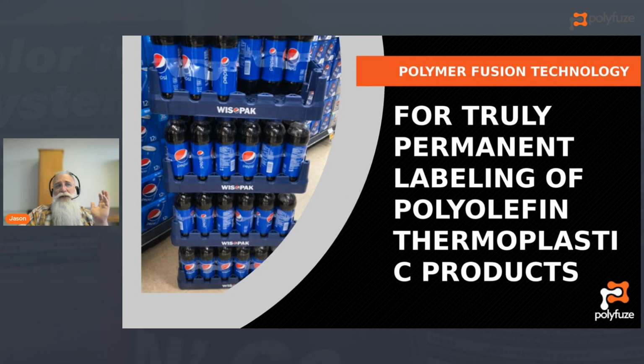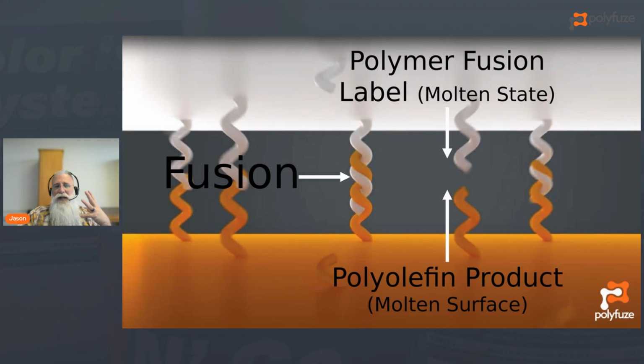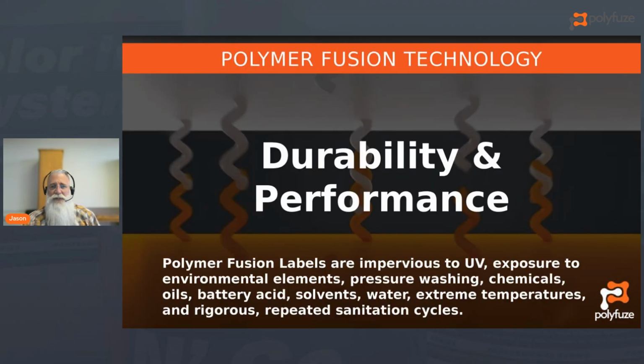And so that brings us to the polymer fusion technology, which we are known for. And this slide kind of tells it all. If you don't take anything else away from this webinar, understand that what we are printing is a plastic label. We're putting it in contact with the plastic part, and then we are melting those two materials together, which is why it works. Think of it more as plastic welding than any sort of decorating technology that we previously spoke about. So again, you're taking two thermoplastics and you're melting them together, hence the polymer fusion. We're actually fusing those two materials together.